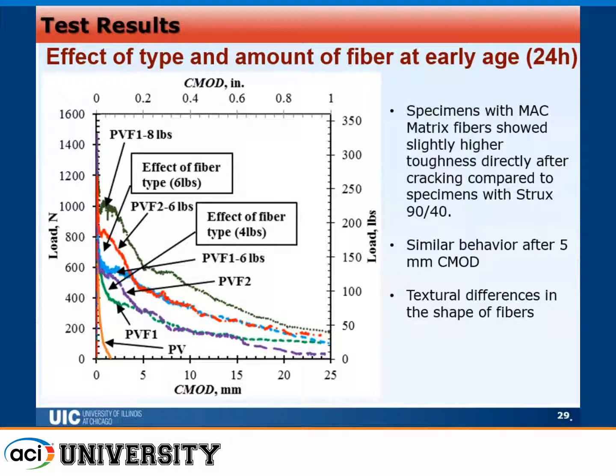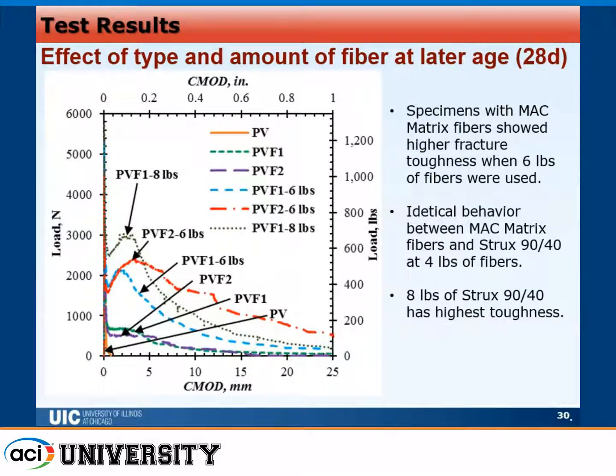Observations here: the difference between the Strux 90/40 and the MacMatrix fibers, in reality they didn't show. They showed very slight difference between them. Only a very slightly higher value at early CMOD values was registered by the MacMatrix fiber, but in general we can say that their behavior is almost the same. The highest fracture toughness value was obtained by the 8 pounds of fibers of Strux 90/40, which showed the best behavior out of all of them.